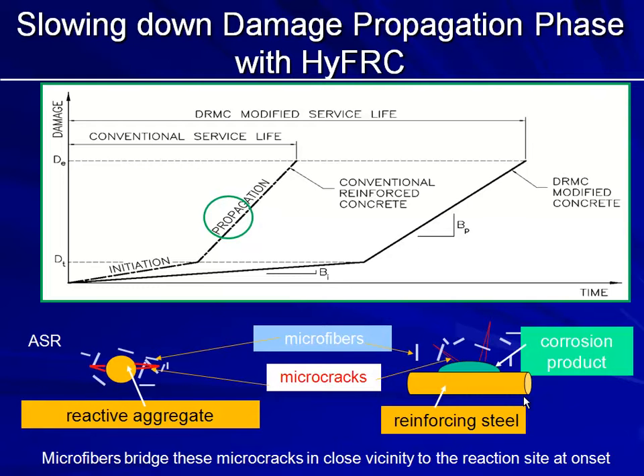Talking about alkali-silica reaction, where does it initiate? It initiates right at the aggregate. That aggregate expands, causes microcracks initially, and we are bridging these microcracks right at the onset. What about corrosion? Corrosion, you have corrosion products right at the rebar. So right here are corrosion products that are expanding, causing these microcracks, and we have the microfibers right there to slow down the cracking of the microcracks. And this is exactly why that kind of propagation phase is being slowed down.